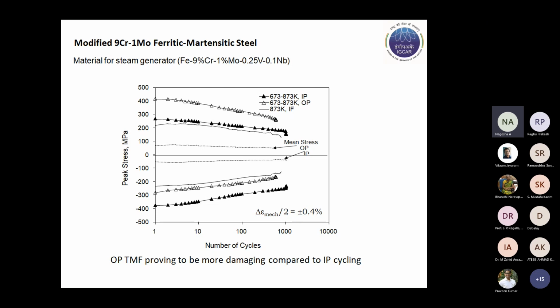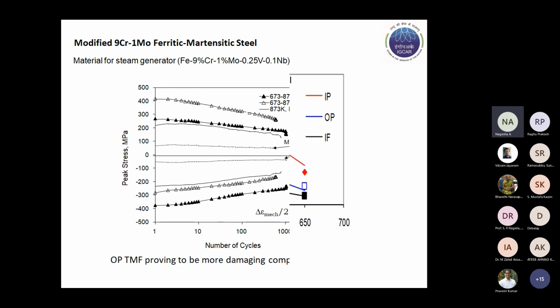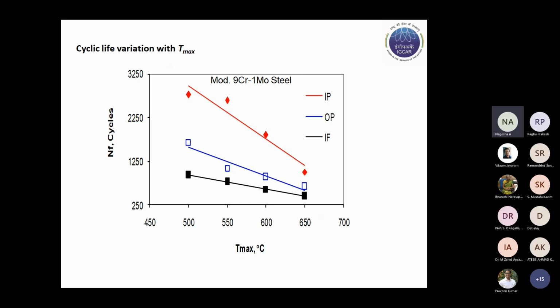And this was investigated under isothermal, in-phase and out-of-phase cycling at different strain amplitudes. In this case, as against the life variation observed in austenitic stainless steel, where we have seen IP cycling giving rise to a lower life, the situation was slightly different. You can see that out-of-phase cycling led to a lower lifetime compared to in-phase, again across all the temperatures investigated.